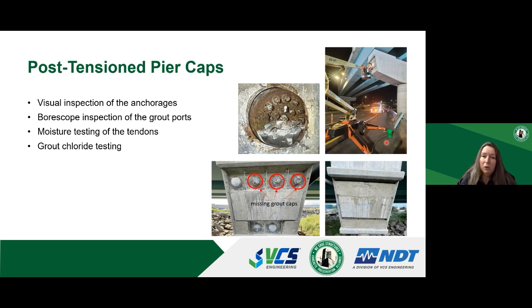Instead, because the anchorages on these pier caps were easily accessible, we removed the pour backs and did visual inspections of the anchorages. As you can see on the slide on the bottom, we found some missing grout caps. And on the top, the image shows that there were voids in the grout caps at some locations. Where there was missing grout, there was heavy corrosion of the anchor plates, as well as strand tails. In addition to the visual inspection, we did borescope inspection of the grout ports, moisture testing of the tendons, and we also sampled the grout for chlorides.